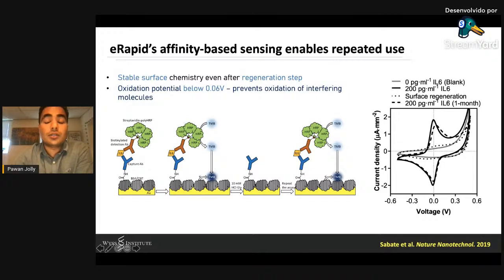Of course, there's a slight drift, but it was really encouraging for us to know that we can actually regenerate the chip, store it for a month and redo the experiment, and we can still get similar peak after 1 month. And this drift could be just not related to the coating, but it could also be just the degradation of the antibodies over time.